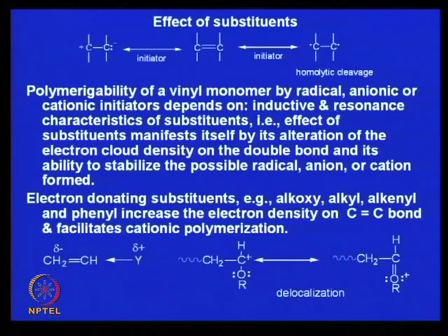Here you look, effect of substituents. As I was telling you, this is the monomer, an olefinic monomer having this pi bond. Now, if some initiator comes close to this monomer, that can polarize, forming a positive center and a negative center, polarization of the pi bond, or it can break into two free electrons, a homolytic cleavage, or heterolytic cleavage.